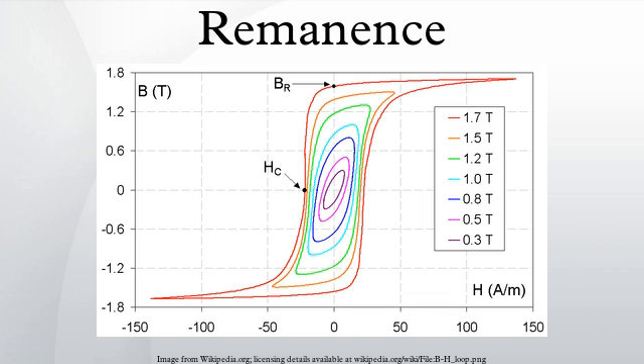In physics this measure is converted to an average magnetization. If it must be distinguished from other kinds of remanence, it is called the saturation isothermal remanence, or SIRM. In engineering applications, the residual magnetization is often measured using a BH analyzer, which measures the response to an AC magnetic field. This is represented by a flux density BR. This value of remanence is one of the most important parameters characterizing permanent magnets. It measures the strongest magnetic field they can produce. Neodymium magnets, for example, have a remanence approximately equal to 1.3 teslas.